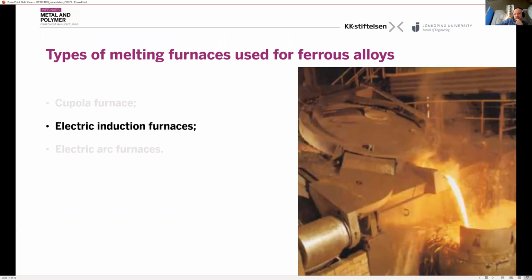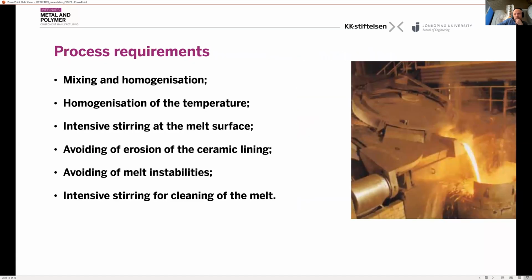The next is about the electric induction furnaces. That is a furnace in which the heat is applied by induction heating of a conductive medium in a crucible placed in a water-cooled alternating solenoid coil. The process requirements within melting with induction furnace are mixing and homogenization, not only of the charge, but also of the temperature, the intensive stirring at the melt surface, avoiding erosion of the ceramic lining, melt instabilities, and intensive stirring for cleaning of the melt.